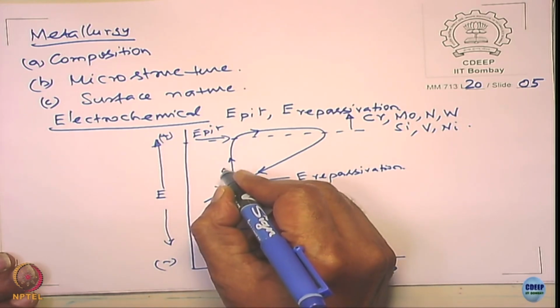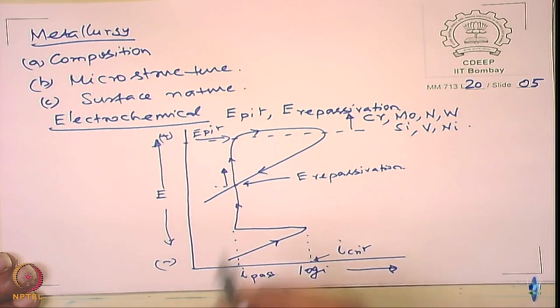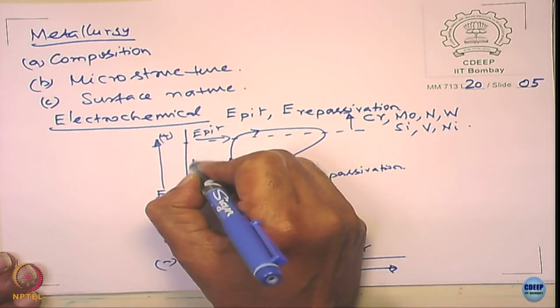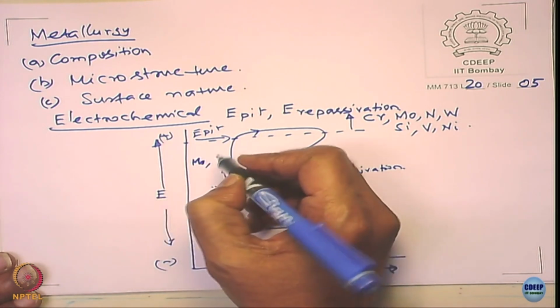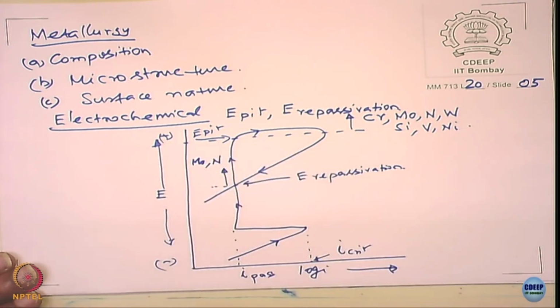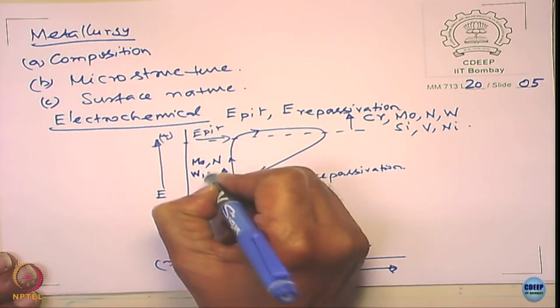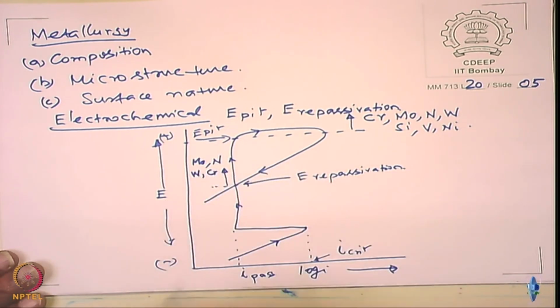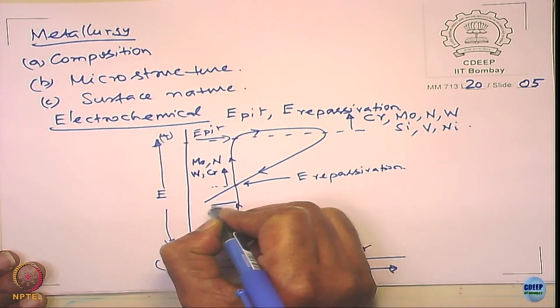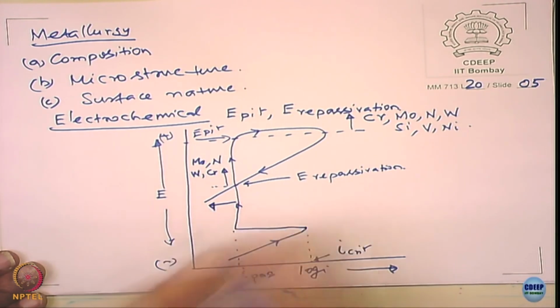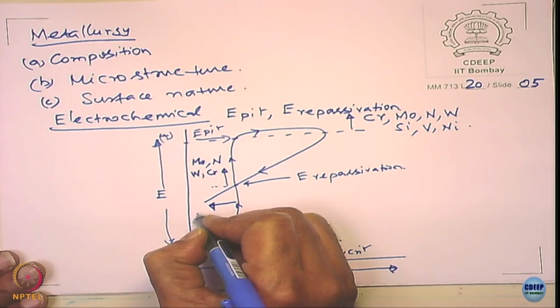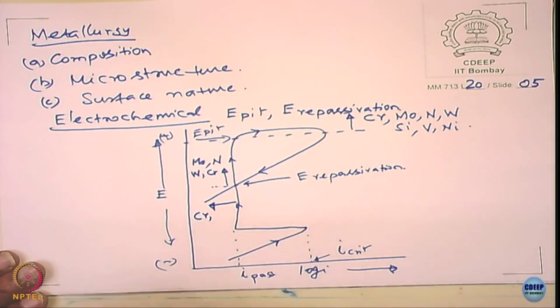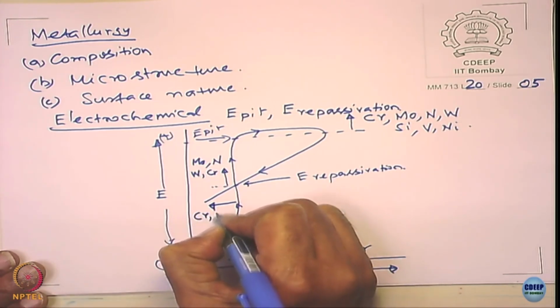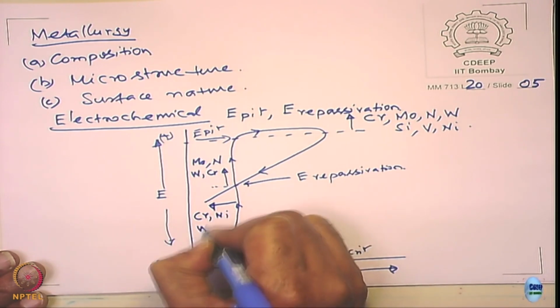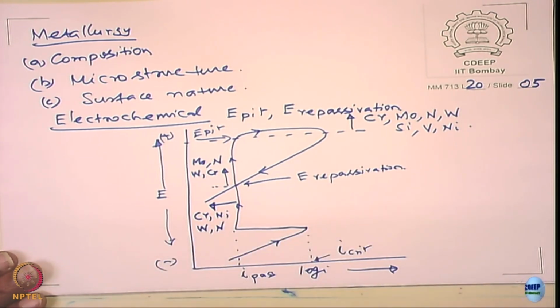What about this? If it goes up, it is good. This is called repassivation potential. If it goes up, these are the elements you have: molybdenum, nitrogen, tungsten and chromium. Of course, you want to know about the passive current density, whether it is reduced or not. The passive current density is reduced by these elements: chromium, nickel, tungsten and nitrogen to a certain extent.